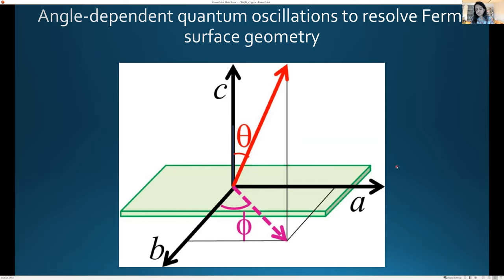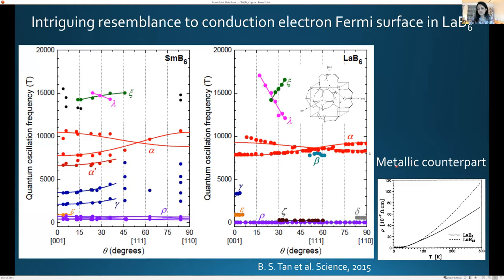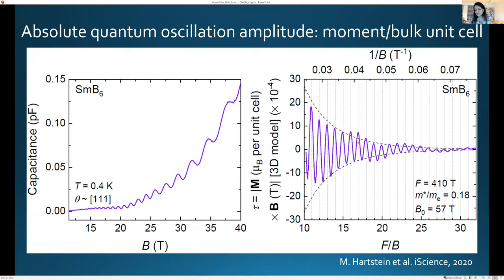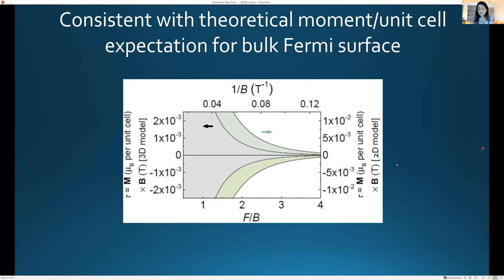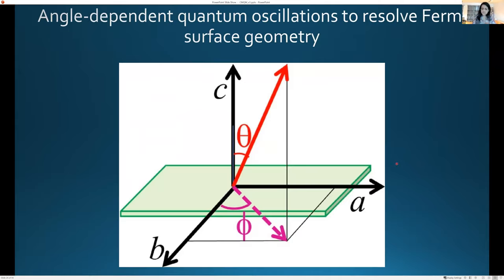And actually, what I should have warned you about is the frequency of the quantum oscillations. I'm just going to go back, for people who aren't familiar with this. The frequency of the quantum oscillations is a measure of the Fermi surface area. So the slower the oscillations in 1 over B, the lower the frequency. The more rapid the oscillations, the higher the frequency and the bigger the Fermi surface area. And if you have different frequencies, that means there are different cross sections of the Fermi surface. So if one rotates the magnetic field and expects the area to change with angle, that means the periodicity of the oscillations will change, for example for a cylinder in a cosine-like way.